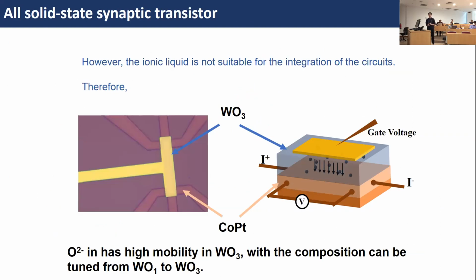However, liquid devices are usually not suitable for the integration of circuits because they are liquid. Therefore, we want to make an all-solid-state transistor. Here we fabricate another synaptic transistor based on the CoPt film. We use tungsten oxide to replace the ionic liquid. Because the tungsten oxide has lots of oxygen ions inside, when you apply the gate voltage, the oxygen ions are pushed into the CoPt film, and some of the oxygen can be trapped in the film. In this way, we can modulate the resistance and the coercivity of this CoPt film.